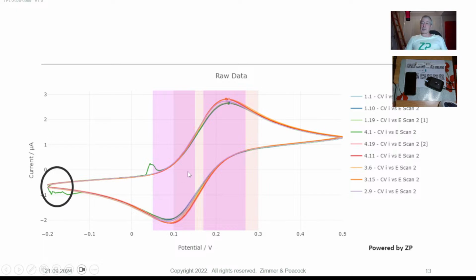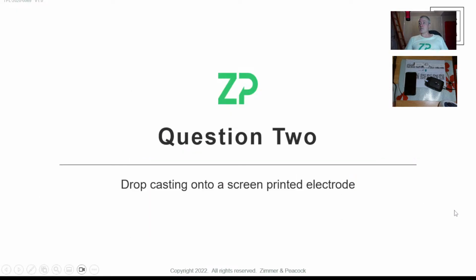Suppose you started the experiment sort of in the middle of your voltammetry. If you'd started it at one of the edges, you may not have had quite such an obvious discontinuity, but it's just where you started the experiment. If you started it, as I say, at what's called open circuit potential, then you may not have seen it quite so much. But often when people are reporting data, they're actually showing you the second voltammogram, so they're kind of hiding, let's say, that. And it's not a problem. It's no criticism of anyone's work. It's just you can see where you essentially started the voltammetry.